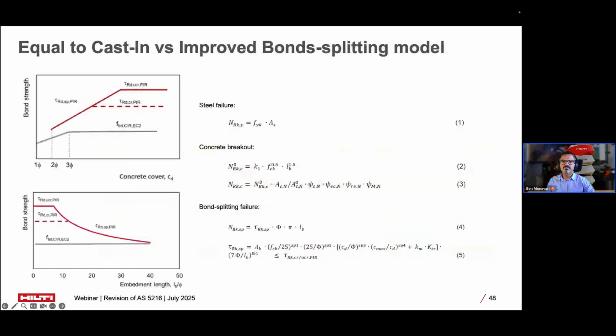The improved bond splitting model accounts for actual stress distribution along the length of the bar. Equal to cast-in assumes uniform bond stress distribution, but in the improved model, the bond stress varies with concrete cover and depth. With high concrete cover, both design methods show increased capacity, but the improved model continues gaining capacity.